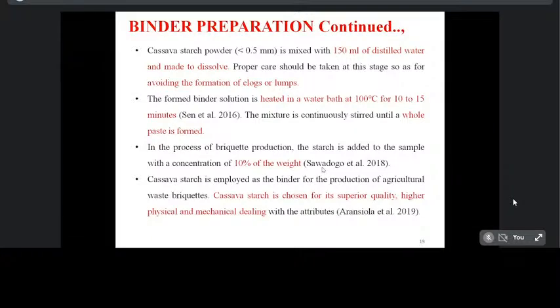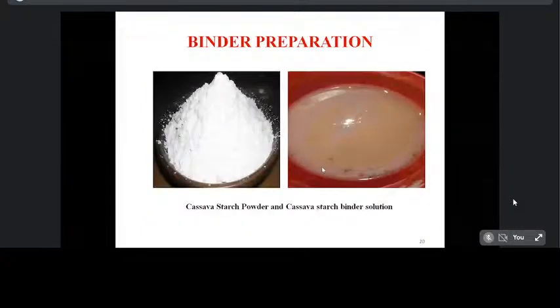In the process of briquette production, the starch is added to the sample with a concentration of 10% of the weight. The produced biomass briquettes take the binder solution added as 10% of the weight. Why am I choosing cassava starch as a binder? It has superior quality and higher physical and mechanical binding while mixing with 2 or more agro waste materials. The first image shows the cassava starch powder, and the second image shows the produced cassava starch binder solution.